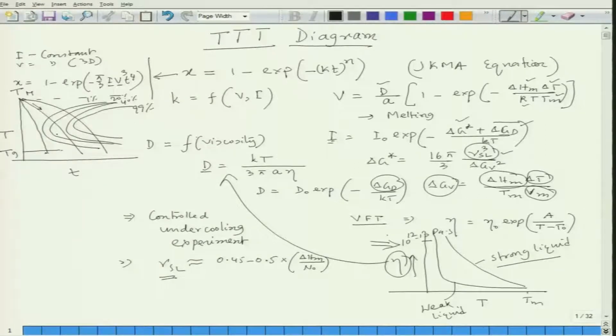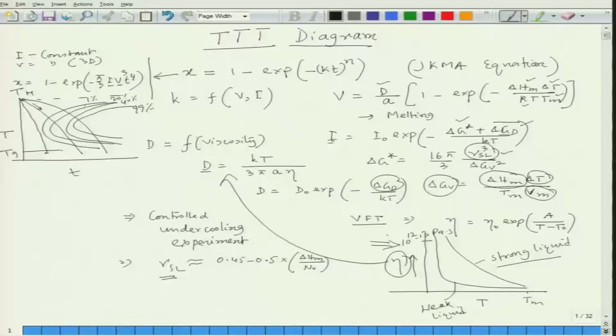So, that means the maximum amount of crystal that would form in that melt is less than 40%. I can say this is close to 30%. And rest of the melt would again reach Tg, it will form glass. So, like that way I can have different fraction of crystalline material in a melt or in a glassy matrix. So, then that decides my temperature, time, cooling rate, all those informations.